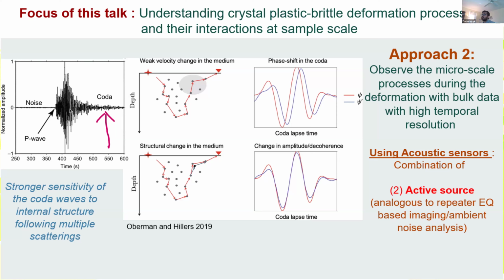In particular, if we send a pulse and measure it at the receiver, we initially have the P wave arrival, because that's the fastest velocity. Then we get the S wave. Then we get some of the surface waves as well as the coda, right? The coda in this context is really the waves that we're getting because of multiple scattering. In the case of the field, that's because of multiple scattering. In the case of lab samples, there's also scattering from the boundaries of the sample.